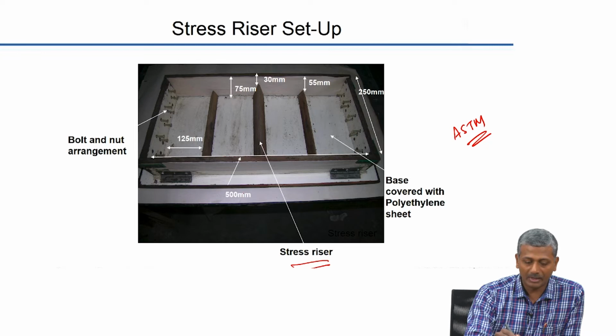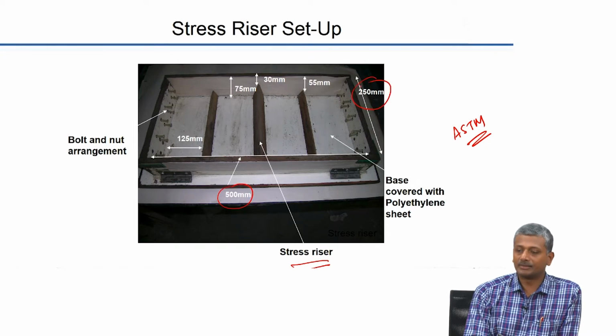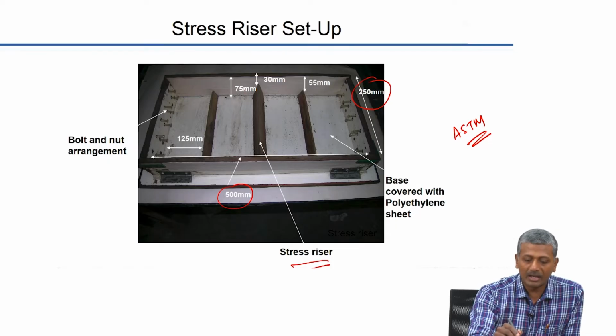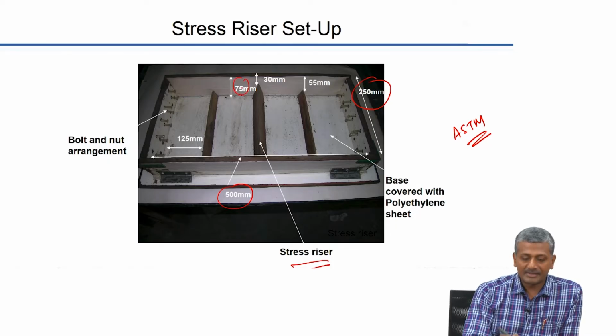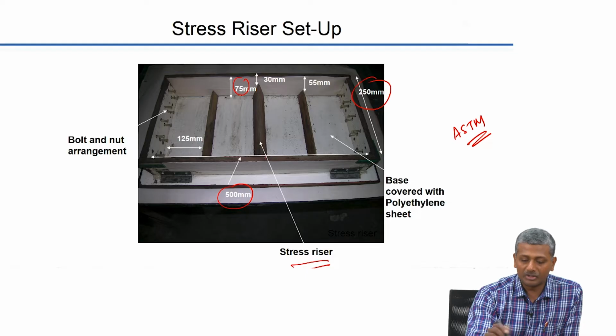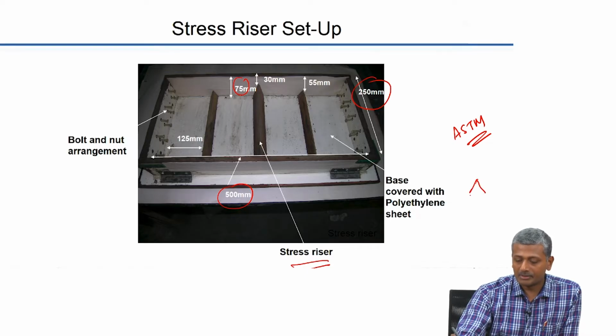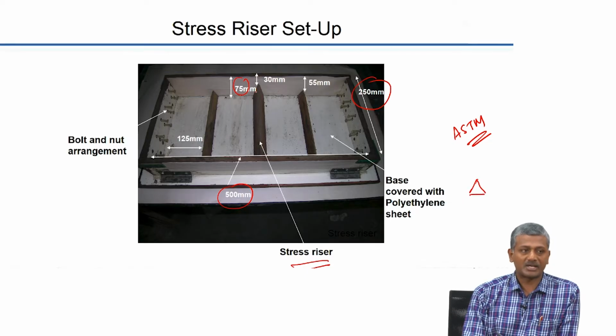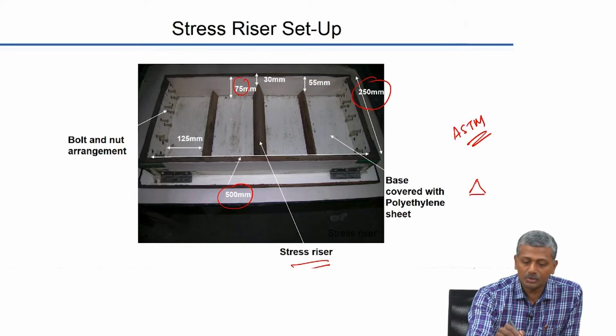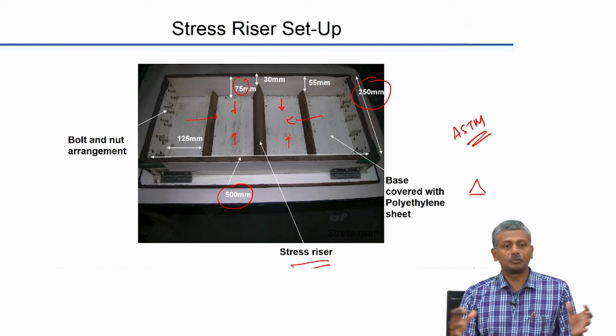Okay, the slab dimensions are 500 millimeters length and 250 millimeters breadth, and it has a total height of 75 millimeters, and in the center of the slab you have a wedge. It is just a wedge which is placed in the center of the slab, which acts like a stress riser. So what happens now is, as the concrete starts to shrink, what will happen? It will try to shrink in both directions.